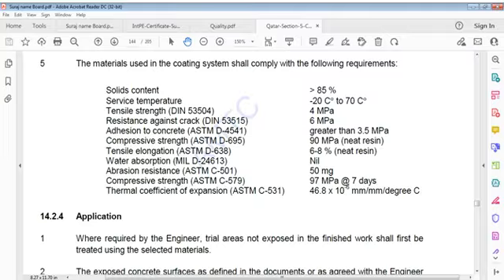That is tensile elongation, 6 to 8% neat resin. Water absorption nil, MIL D-24613. Abrasion resistance, ASTM C501, 50 milligram.